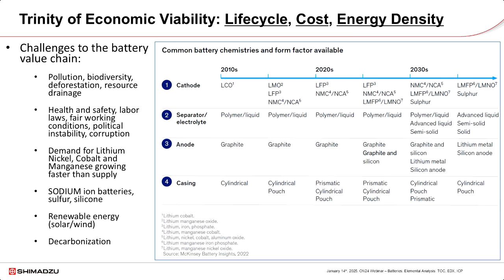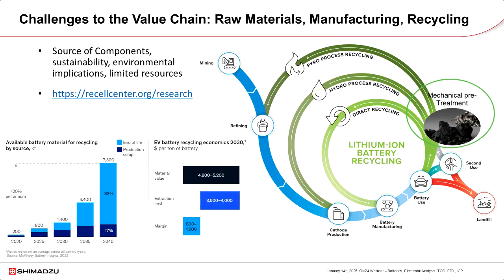The most common recycling technology is to render batteries and electronic components into black mass powder by physical and thermomechanical processing. These result in a complex mixture of organic and inorganic materials. Analyzing these can be challenging because of the high total dissolved solids, extremely wide range of concentration from ppt to tens of percent levels, the insolubility of the materials in acids, and the presence of electrolyte solution residues, organics, and halides.